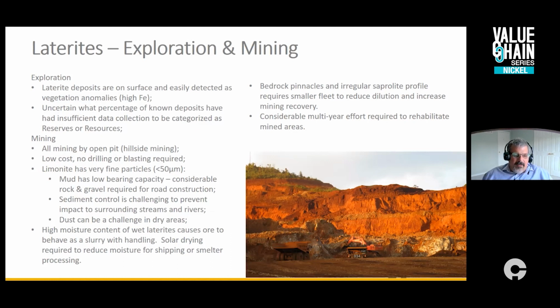And this high moisture content, both in the limonite and the saprolite, gives material handling problems. It behaves like a slurry when it's being handled. It needs to be dried with solar drying before it can be put into ships. There've been several accidents with ships sinking due to too high a moisture content in the ore on ships between Indonesia and China.